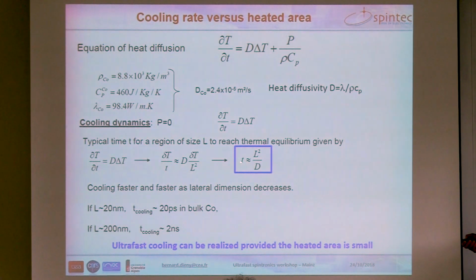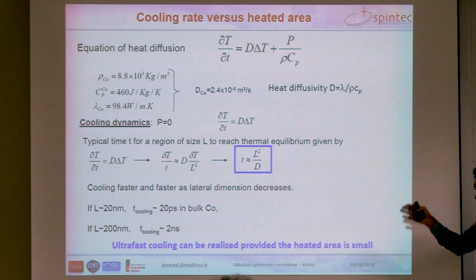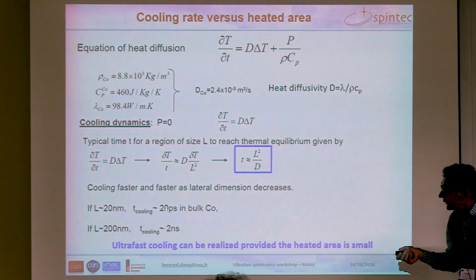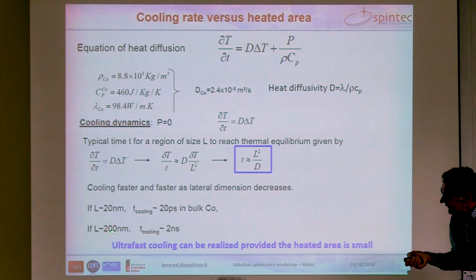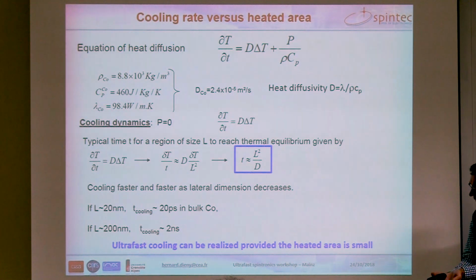And so we can have an idea of the time of the cooling as the ratio of the square of the heated size, so basically the heated area, divided by this diffusivity constant. So if we take a material like cobalt, we can, from this expression, calculate that if we heat 20 nanometer of cobalt, so a kind of hemisphere of 20 nanometer of cobalt at the surface of a bulk cobalt, then we will cool in 20 picoseconds. Now, if we heat a hemisphere of 200 nanometer, this one will reach thermal equilibrium in 2 nanoseconds. So this shows that we can get ultra-fast cooling provided we heat a very small area.